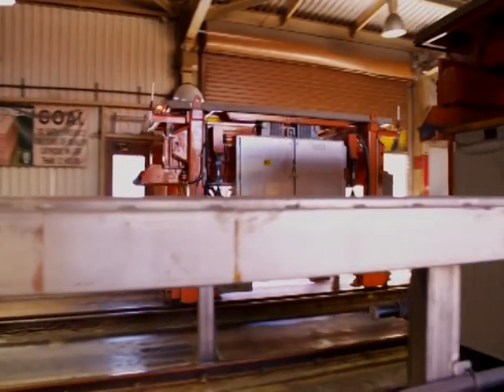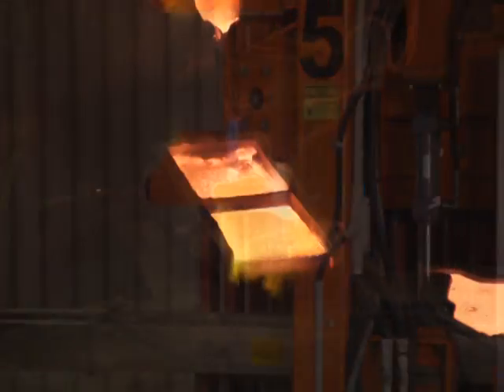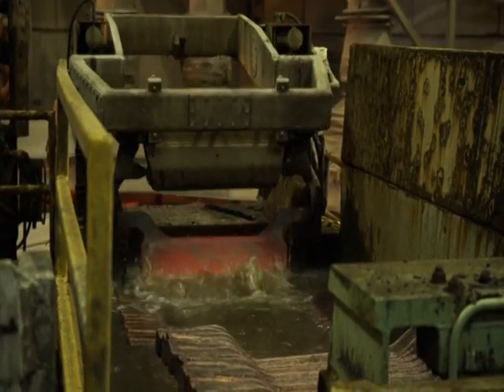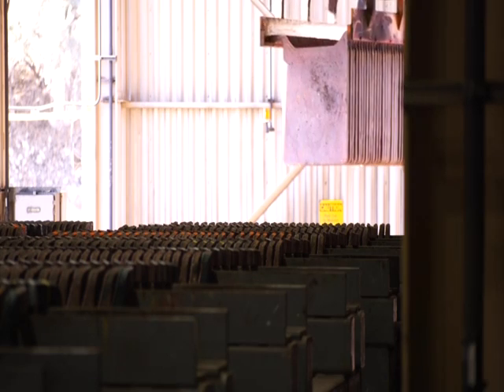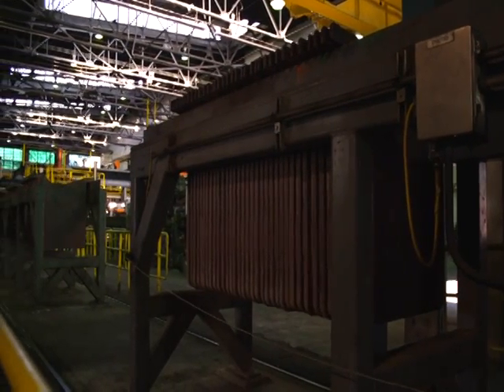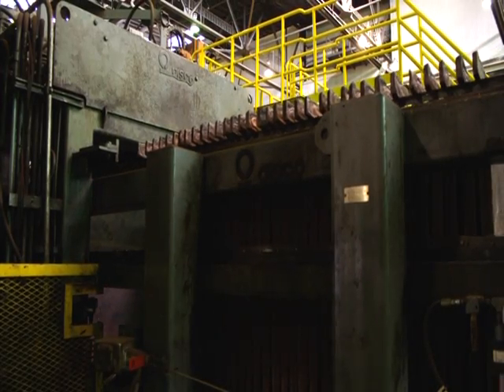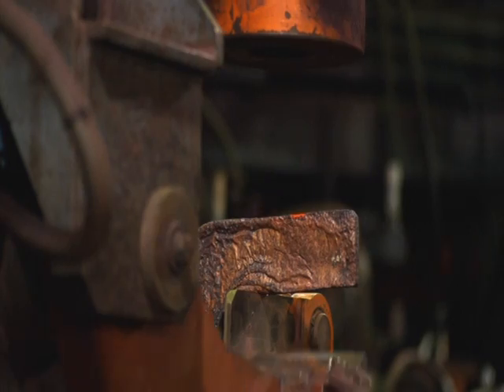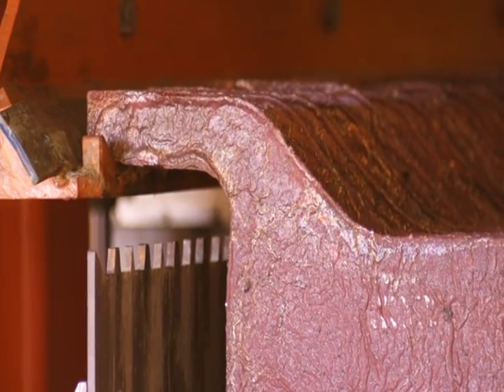Here is the process of creating a cathode in 2010. First, the refinery relies on the neighboring smelter to provide 750-pound anodes that are 99% pure. About 1,200 tons of anodes arrive at the refinery on railcars daily. Anodes are transported from the railcars to the anode preparation machine, where they undergo seven steps to assure they meet the refinery's required specifications. Those that do not measure up are shipped back to the smelter, where they are recycled to make new anodes. At the preparation station, they are weighed and measured, and the ears of the anodes are straightened and machined so they hang plumb alongside stainless steel blanks in the tank house cells. Finished anodes are conveyed to custom-designed racks, where 47 at a time are loaded on the refinery's automated rail transfer car system and sent to the tank house.